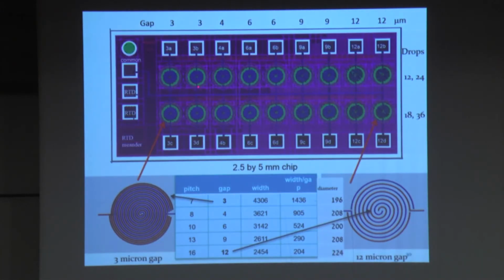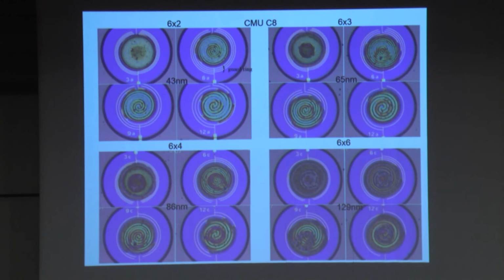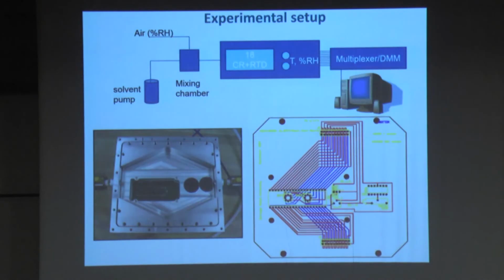Okay, these are 3 micron gaps, 4 microns, 6, 9, and 12, 2 rows. There's also a meander temperature sensor right here. We jetted on top of it either 12 or 24 or 18 or 36. So in one chip, which is of size 2.5 by 5 millimeters, we can make an array of 18 sensors, which is remarkable, I think. This is how these jetted devices actually look. Okay, it's almost perfect jetting. Well, not always, but most of the time.